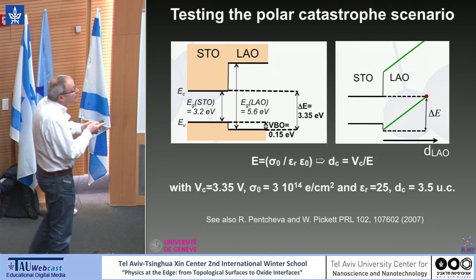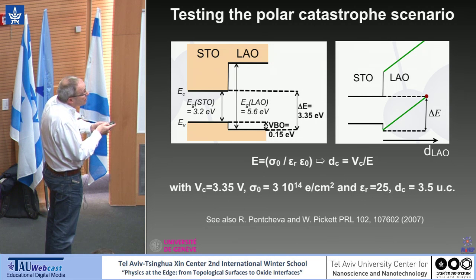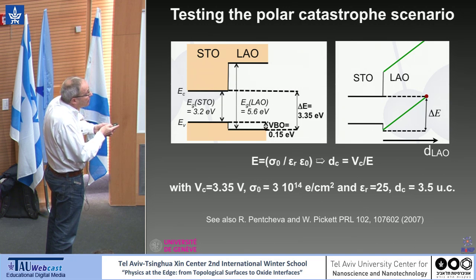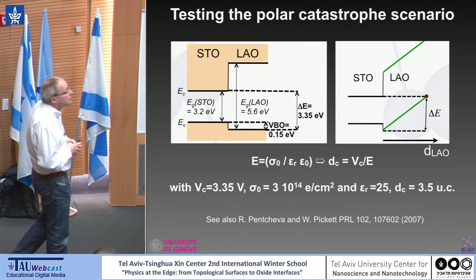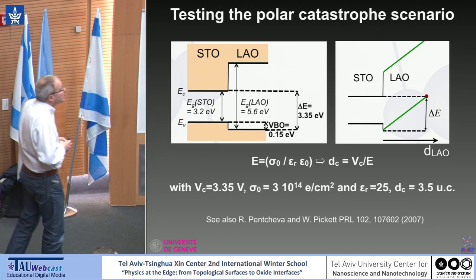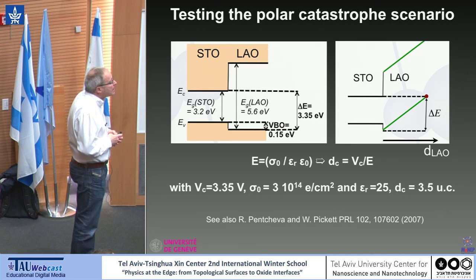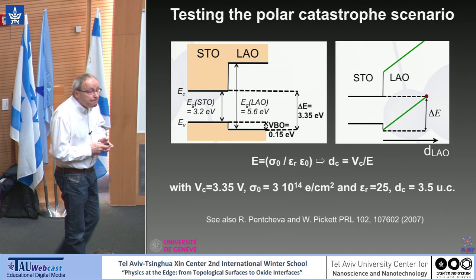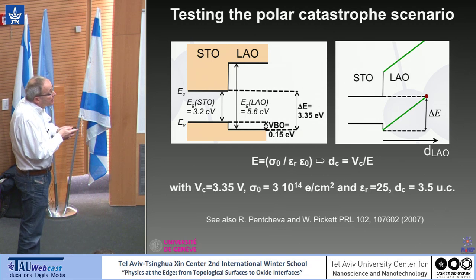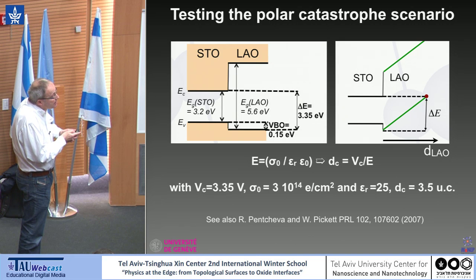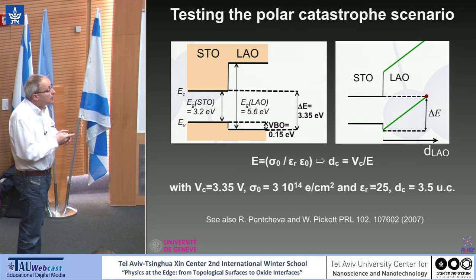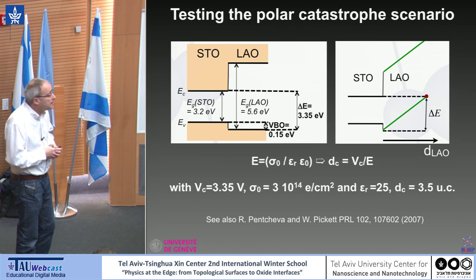And at some thickness, you reach the bottom of the conduction band of STO. And here, you can have a Zener breakdown, and you can transfer charges from the top to the interface. So what it means is that this model predicts that if the thickness of lanthanum aluminate is below this thickness, the system should be insulating, and above it should be conducting.